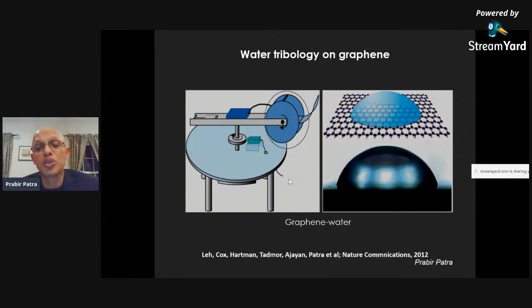The reason this work was accepted again in Nature is because we first showed that in this particular case, it doesn't follow those curves. The time at which the water molecule drops is invariant of the force it takes, invariant of time. It goes very fast. In other surfaces, it takes 8 to 10 minutes to have the curve stabilize. In this case, it's in a few seconds. And there is no upward trend to plateau. It just goes parallel to the x-axis.